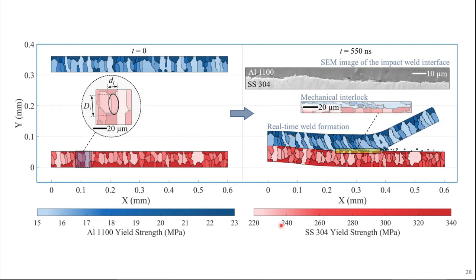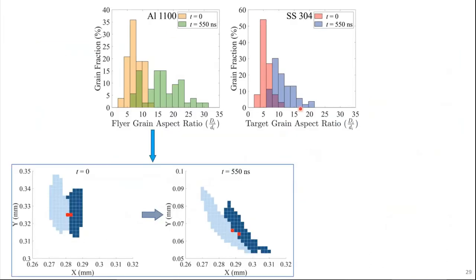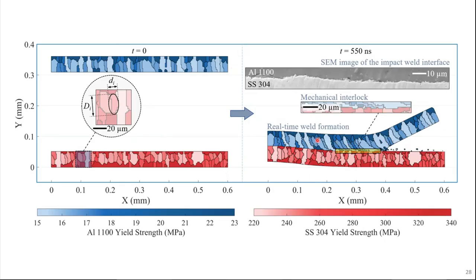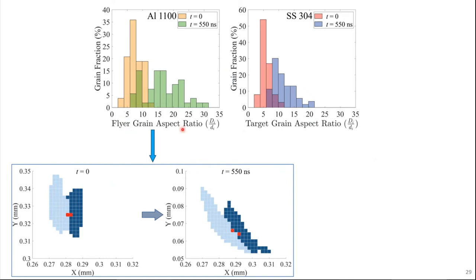The color schemes I've used over here are based on the different yield strengths, which are, as I mentioned before, determined via the Hall-Petch relation. We noticed during the weld formation a lot of shear effects and stretching in the grains of aluminium. So just to examine what's happening along these grain boundaries in our simulation, we plotted the grain aspect ratios. If you think of an elliptical fit, that's just the ratio of the major diameter, capital D, to the minor diameter, lowercase d. At T equals zero, we get this histogram over here for aluminium. At T equals 550, we get the green histogram. So you notice there's a definite difference. It's almost a threefold difference for aluminium. Likewise, for stainless steel 304, it's almost a twofold difference between T equals zero, which is the red histogram, and T equals 550, which is the blue histogram.